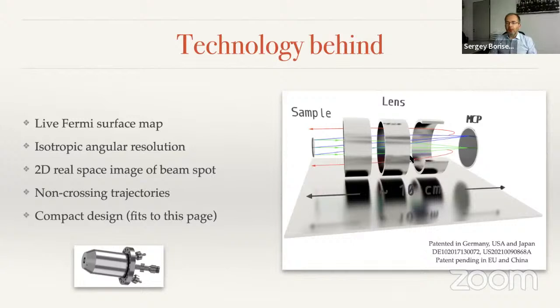What is new is that in this case, we use the surface of the detector to repel the electrons which we do not need, basically the slow electrons. With this, we do a low-pass filter, which means that we can detect only electrons which have energy higher than a particular value, which is set by the repelling voltage of the MCP. This is illustrated by the red beams, showing that the electrons which do not have sufficient energy are just reflected back. With this technology, one could see the Fermi surface live on the screen. I will show it later on.